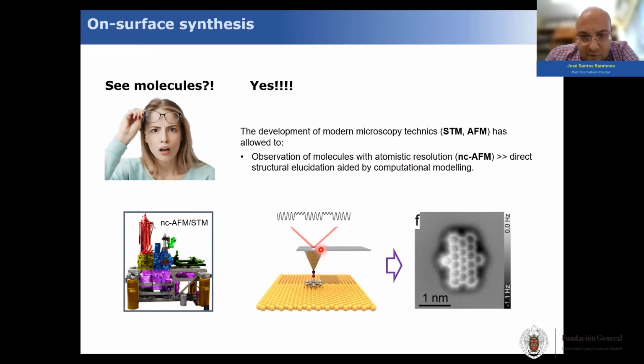AFM. This is the tip of the microscope, which has attached a molecule of carbon monoxide. So by tapping on the surface, you can map, and as you can see here, by the scale of colors, you can see that the darker colors means that the depth is very deep. And if you go to brighter ones, you have higher profiles. So in this way, we observe the molecules with atomistic precision.